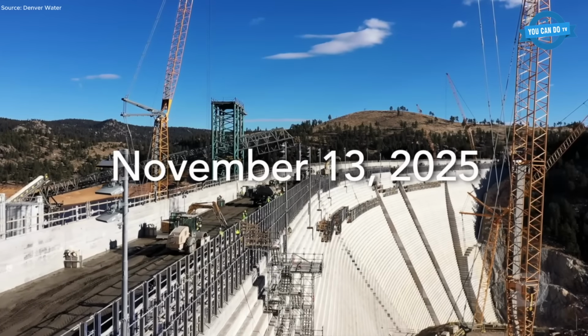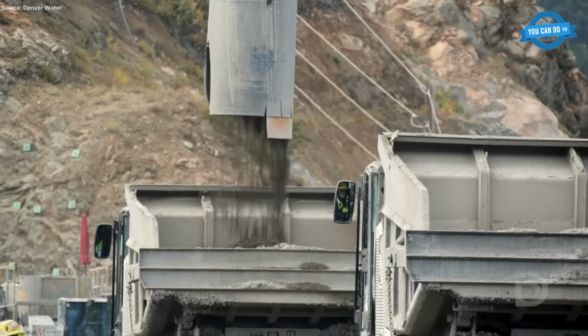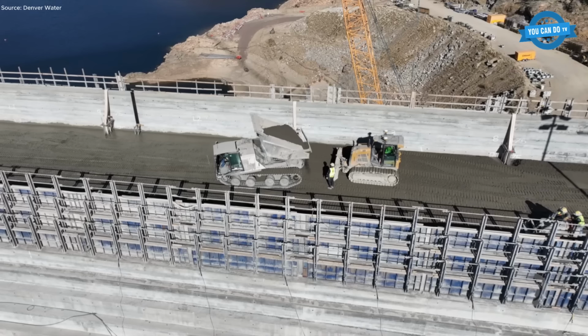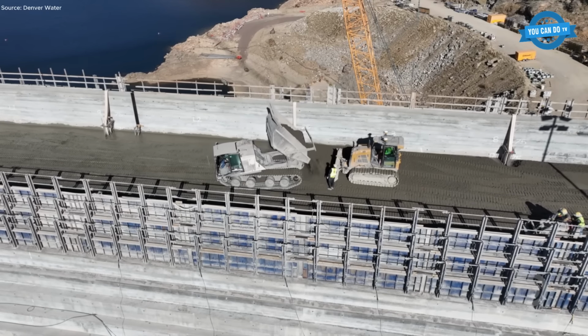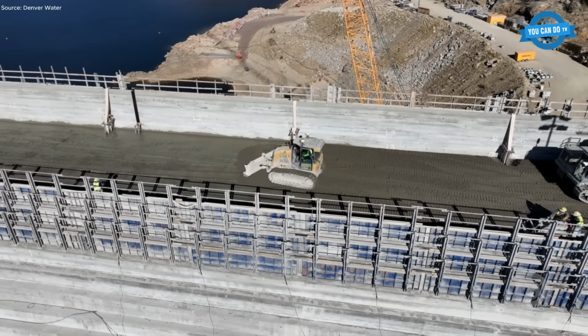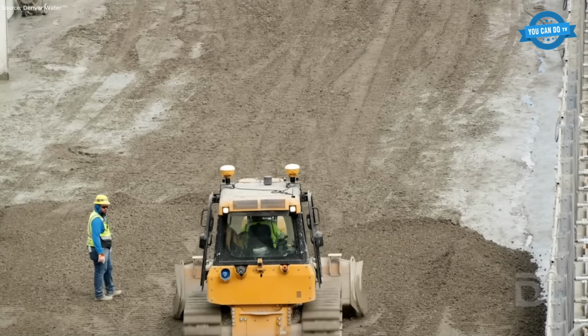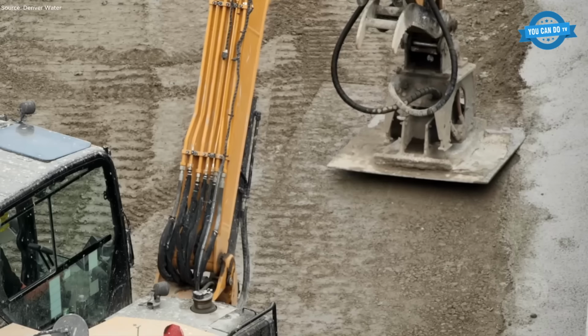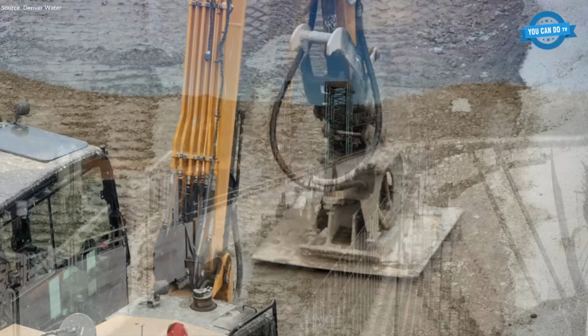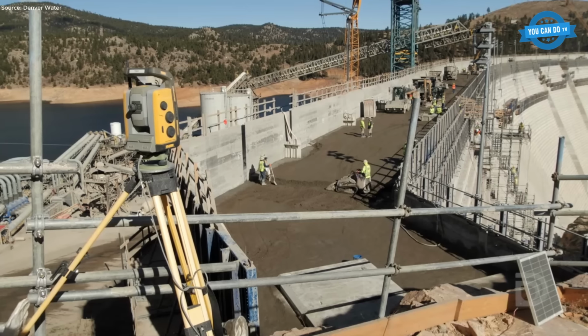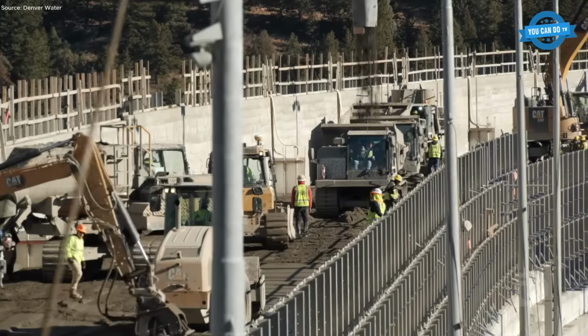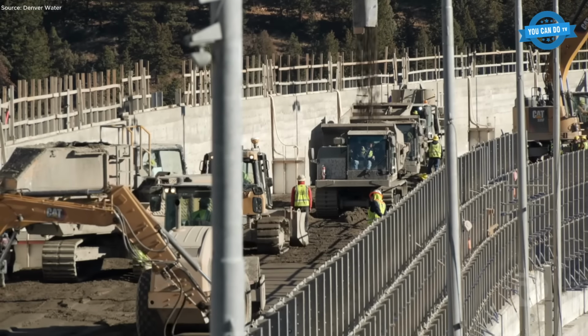Placement operations averaged slightly more than 1 vertical foot per day. Concrete was delivered, spread by bulldozers equipped with GPS-grade control and compacted using vibratory rollers to achieve a uniform 1-foot lift thickness. Survey crews verified elevations after each layer to maintain strict geometric tolerances. Continuous water curing was applied to ensure proper hydration and bonding between successive lifts.